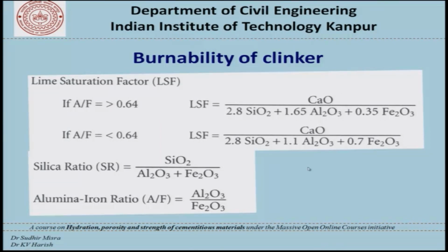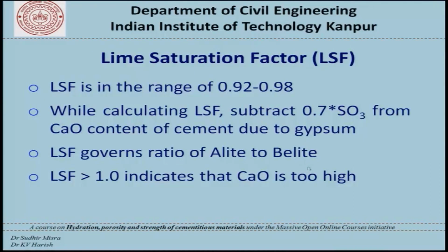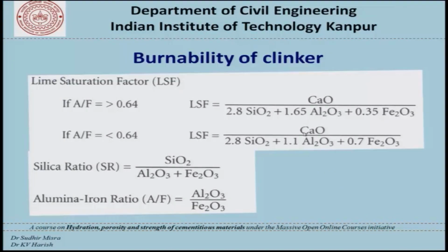For this purpose, we have to subtract 0.7 times SO3, which is the molar equivalent for the calcium oxide that is present in gypsum. So, if we subtract that from the original calcium oxide, then we can find out the LSF.